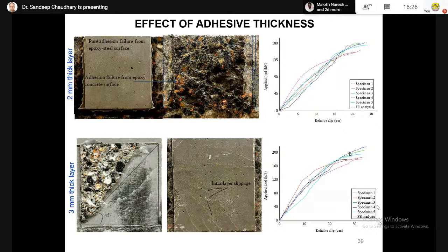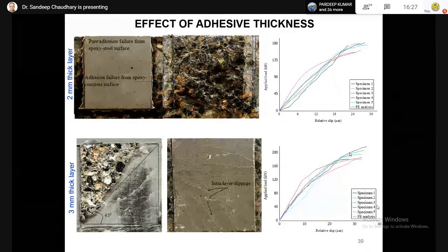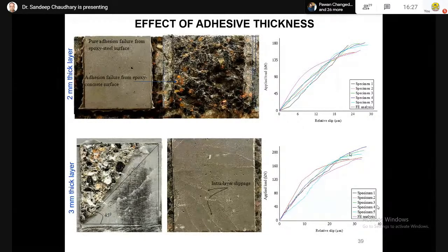But when we used a 3 mm layer, when we increased the thickness of the epoxy, instead of a pure adhesion failure, we observed intra-layer slippage. So that tells us that the thickness of the epoxy layer is also quite important while defining the behavior of composite action or the composite behavior of epoxy bonded sections.